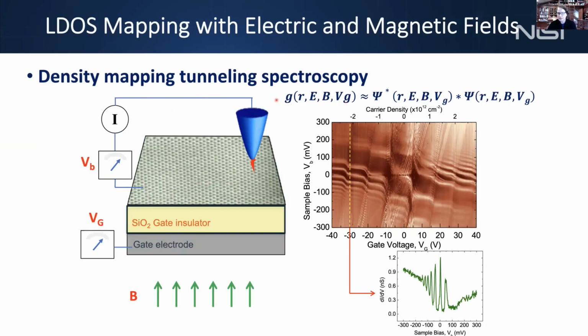So this is really an LDOS measurement in this fourfold manifold. So we don't see well in fourfold space, so we typically show this in 2 dimensions. We pick out 2 variables, for example, in this case, bias energy, and this is gate voltage or density. So to understand this map, just remember that 0 is the Fermi level.